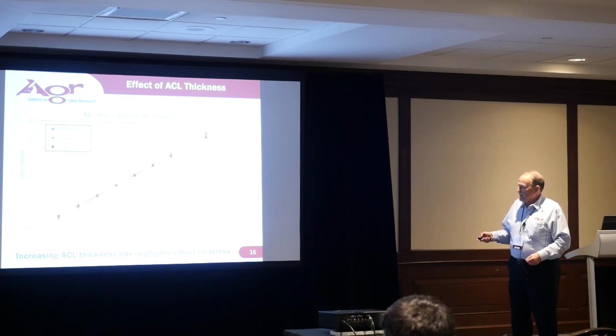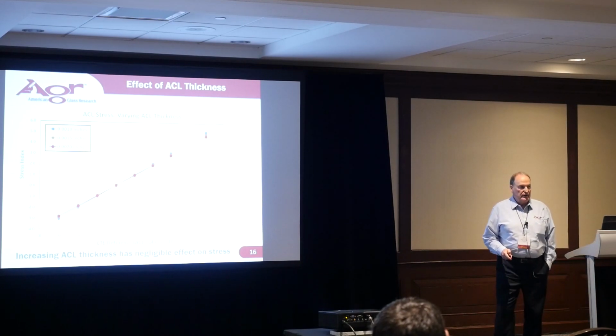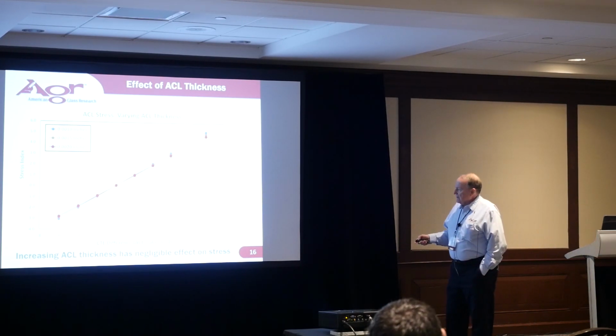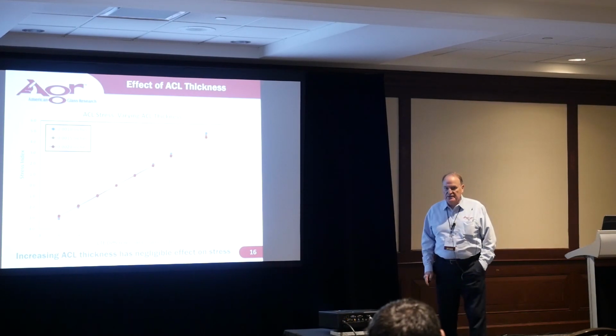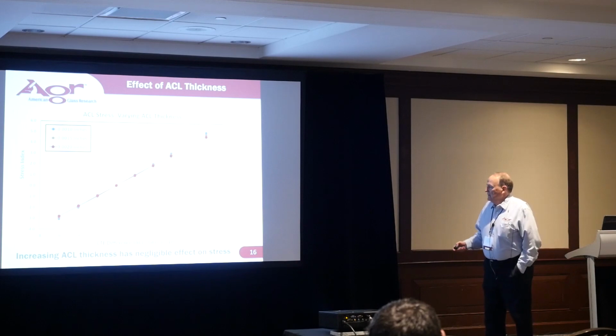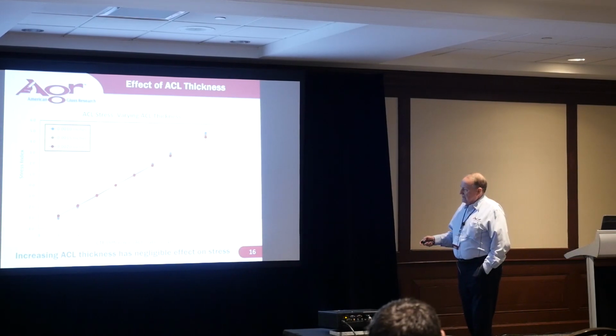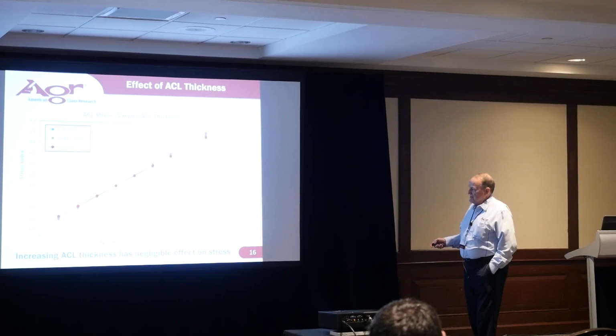The x-axis is the difference between the coefficient of expansion of the ACL and that of the glass. So if we take a look here at 0, the values to the right indicate that the coefficient of expansion of the ACL is larger than the glass. If we go to negative values, that indicates that the coefficient of expansion of the glass is larger than the ACL.